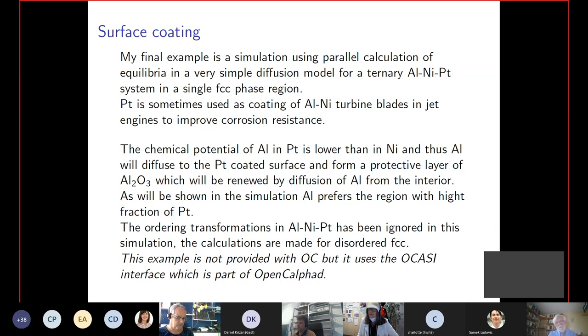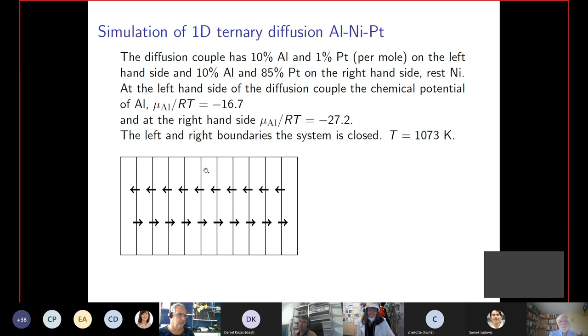Thermodynamics doesn't include time. Time is something you have to add on externally from thermodynamics. So I set up a grid where each of these represents a different composition, and you can have a movement of the atoms between these grains. On this side, I have a platinum-rich surface, and this is the interior of the turbine blade where you have no platinum originally. And 800 Celsius is about the temperature you are at up in the air when the plane is moving from one city to another.